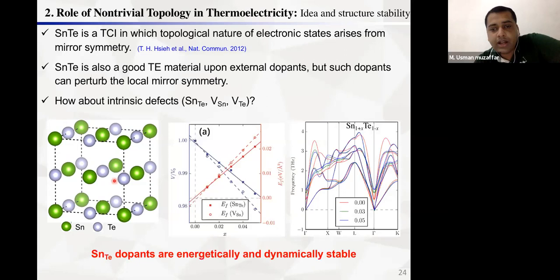So in our case, we consider these intrinsic defects, and we find that the formation energy of the anti-site defect is lower than that of the vacancies. So anti-site defects can be created experimentally. Then we calculate the dynamical stability, and you can see that the phonon frequencies are all positive. So it means that it's dynamically stable. So energetically and dynamically, we can create the anti-site defects. So experimentally, we can create these anti-site defects in this system.